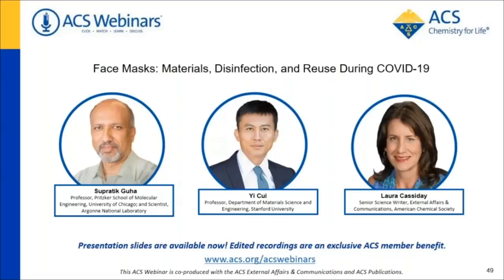So with limited testing, we have been doing 75 degrees Celsius, I think 30 minutes treatment, and the fit testing is fine. But with that said, we have not done extensive fit testing after that, for practical reasons: the number of masks available and the fit testing instrument availability. But I think it's important down the road to test 95 and 85 degrees Celsius after heat treatment. From visual inspection, they look fine, but require more detailed testing.